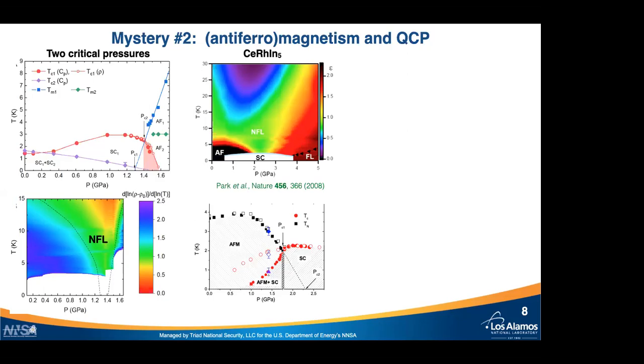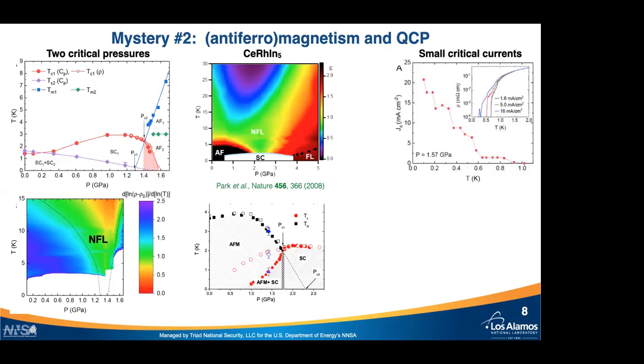This is the phase diagram of CeRhIn5 as well, with both heat capacity and resistivity measurements. You can in fact see that the superconducting transition temperature from resistance is higher than that from heat capacity, similar to UTe2 as well. In this coexistence region, the critical currents are very, very small. Here's a critical current plot, and you can see that we have something of the order of milliamps per centimeter squared, whereas at ambient pressure, one has a critical current that is kiloamps per centimeter squared.